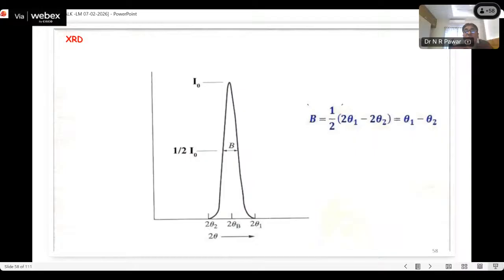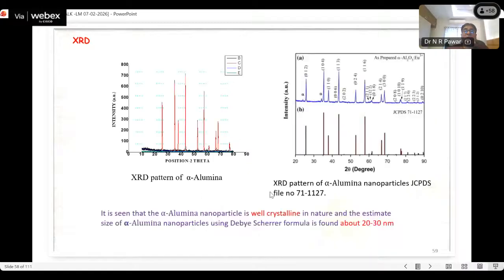And now, what is the B? B is the width of this highest peak. We consider the highest peak, and from that we obtain the width, that is B, and B is equal to half of 2 theta 1 minus 2 theta 2, that is theta 1 minus theta 2, then we obtain B. We consider the highest peak intensity. In the next slide we will discuss in detail.